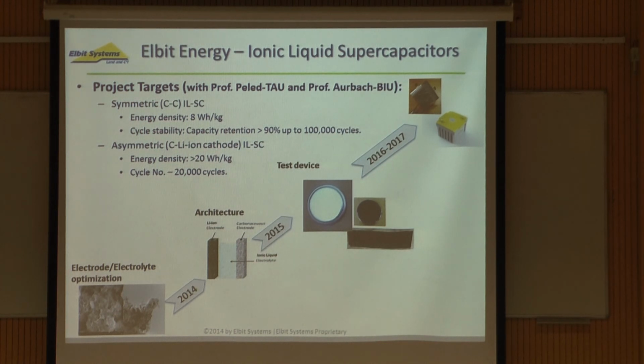But there are ways to tackle it, and we believe that at the end of 2017 we will achieve, at least in terms of engineering prototype, the desired energy density of 20 watt-hour per kilogram, the number of cycles that have to be beyond 20,000 cycles, without actually reducing the specific power density that we have today within the aqueous capacitor, which is somewhere around 1 to 3 kilowatt per kilogram.